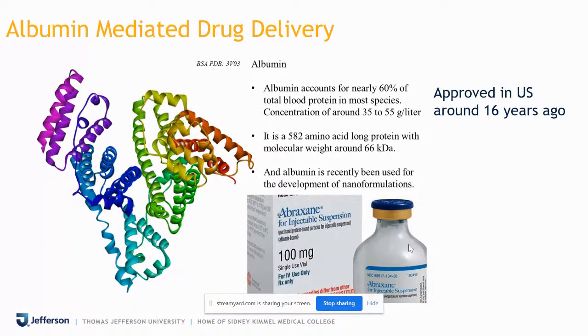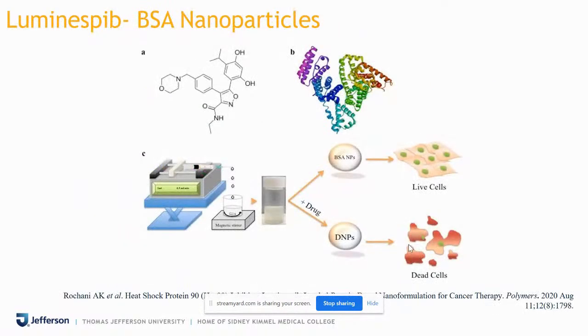This formulation is still in clinical trials, where multiple drugs are used for treatment of some cancers which are difficult to treat using monotherapy. Based on this concept, we thought that we could develop luminespib, which is NVP-AUY922. If you remember, I showed you another drug, an HSP90 inhibitor, which was developed in London. It's a luminespib BSA nanoparticle system. As you can see on the slide, it shows the structure of luminespib and the structure of albumin. We used a simple desolvation method for creation of this nanoparticle solution, and it was used for treatment of MCF7 and MIA PaCa-2 pancreatic cancer cell lines.